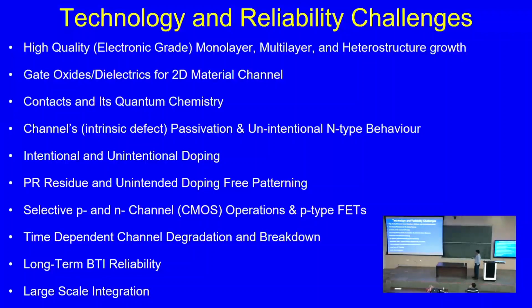Also building a selective n-type and p-type channel for CMOS operation was a challenge. Then what we discovered, there was a time dependent channel degradation breakdown. Now this is not there in silicon. For example, in silicon, if you apply a certain field, no matter for how long, as far as the field is below the breakdown, the channel will remain intact, nothing will happen, right? I'm just talking about, just take a silicon block, apply field, nothing will happen.